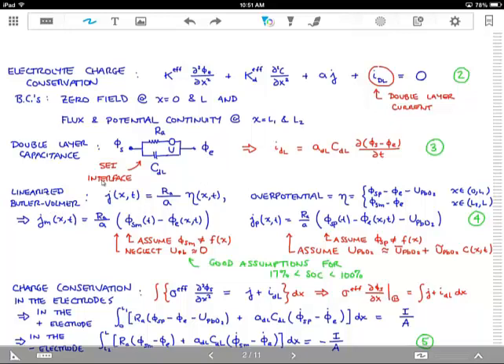Okay, so as I mentioned, there's a relation between current and overpotential in batteries. The overpotential for a lead-acid battery, depending on whether you're in the negative or positive electrode, is phi sp minus phi e minus UPbO2 in the positive electrode, and phi sm minus phi e in the negative electrode. In the negative electrode, there is some UPb, but it's pretty low, so we just basically neglect it here. And again, this is a linearization of that nonlinear relationship between J and eta, which is fairly accurate as long as your C rate is not too high.